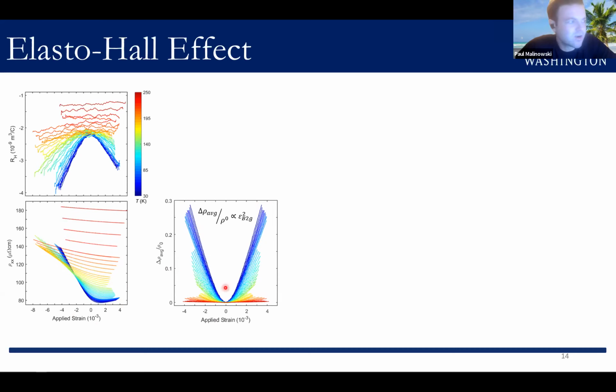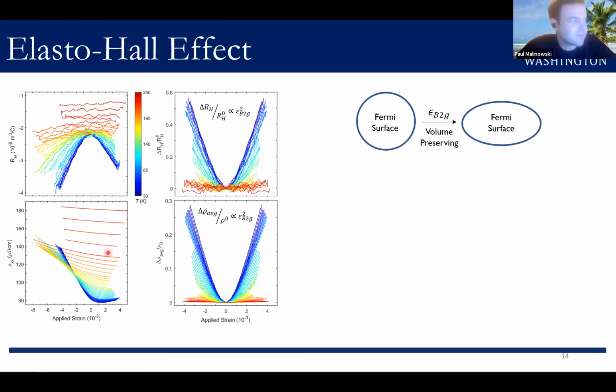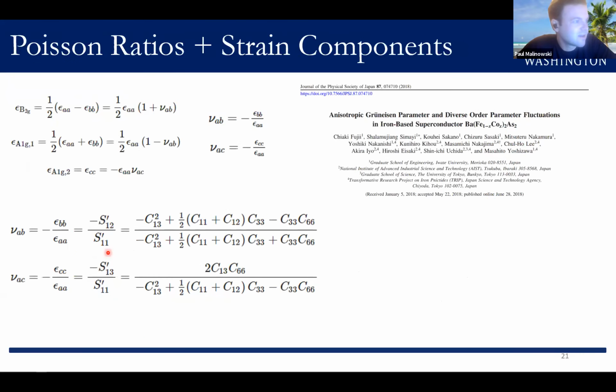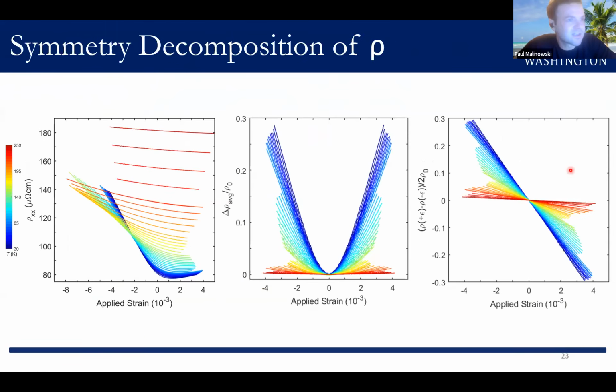So this component exhibits this quadratic increase, which suggests that there's increased scattering in the average resistivity. The anti-symmetric component, which is rho XX minus rho YY, is basically giving you the nematic susceptibility of the sample. So that's why you have this anti-symmetric linear component. And here I can show you actually. That basically looks like this on the right, which is consistent with a diverging nematic susceptibility. So I'm not sure if that answered your question.